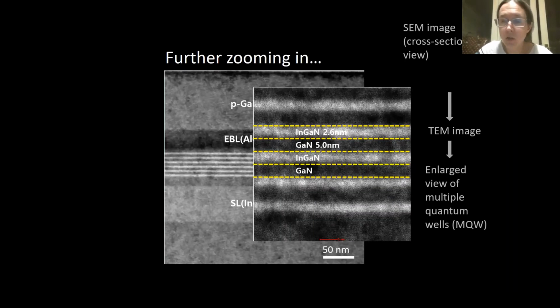Okay, this is just to show you just how tiny these structures are. So these layers now are 2.6 nanometers in thickness. So a nanometer is a billion times smaller than a meter. And typically an atom is maybe 10 times smaller than that. So a single atomic layer in gallium nitride is about 0.25 nanometers. This is kind of 10 atomic layers of material, extremely thin layers. This is actually, though, the bit of the device that really gives out the light. And this is the bit we need to understand if we really want to know how an LED works.